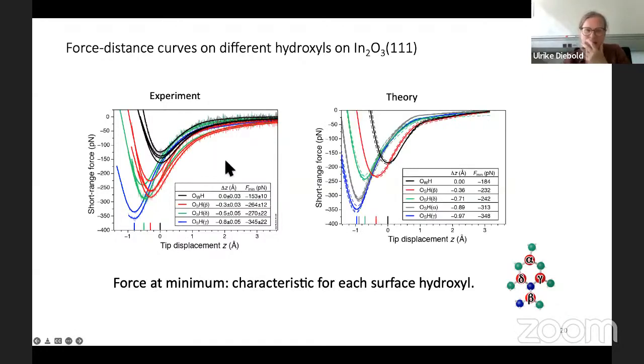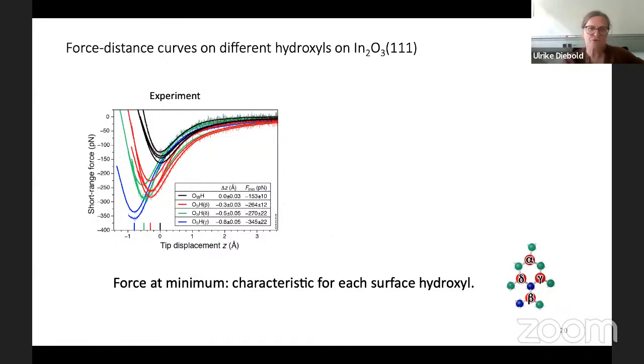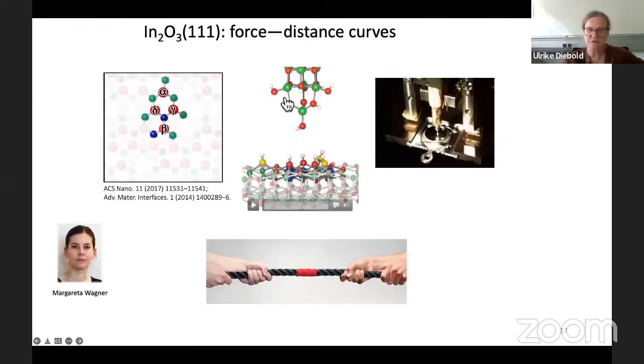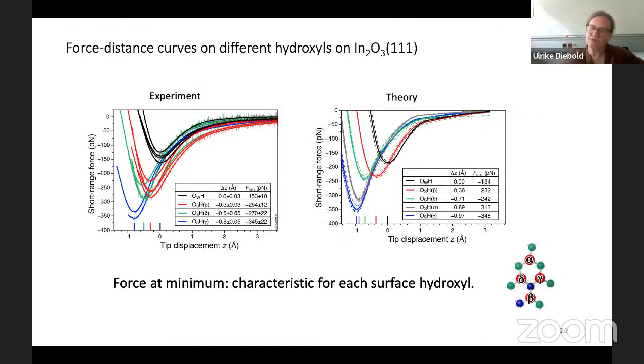And the nice thing is that we then calculated and just modeled this in theory. So what I showed you before, these movies here, these are actually DFT calculations. And then you can do the same thing in these calculations and get the same type of force distance curve. This is the same Y and X axis. So, you know, there's really very good agreement. For example, here, the minimum, I don't know which one I should look at, maybe the minimum here is 345 piconewtons, and here's 348 piconewtons in theory and experiments. So there's really quantitative agreement, which gives a lot of credibility to the calculations, actually. So we understand qualitatively these curves.